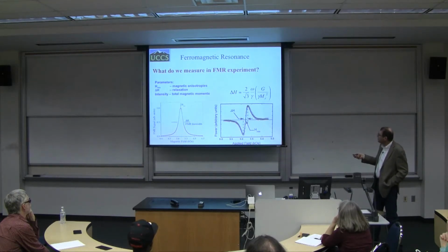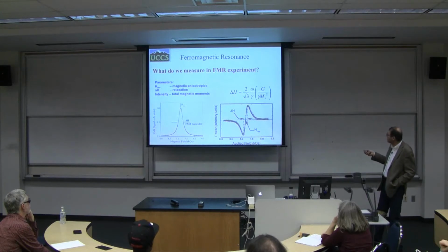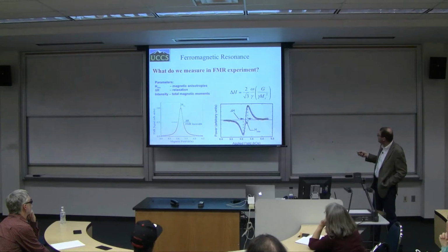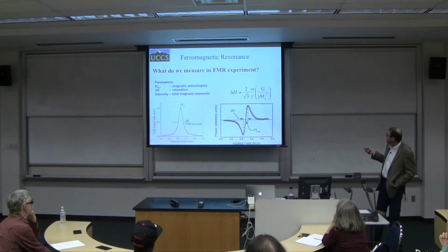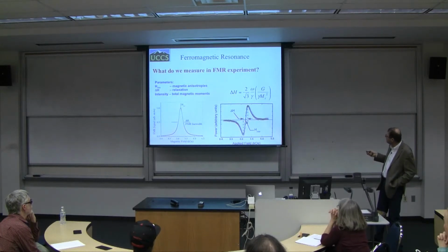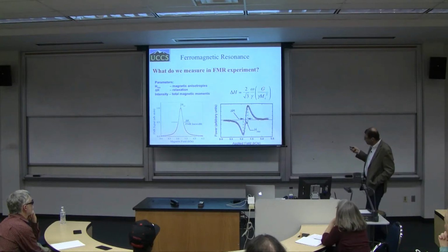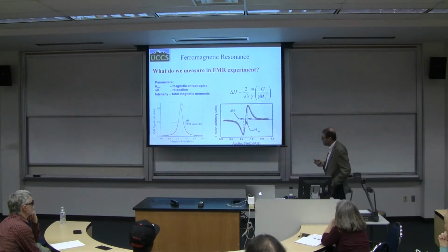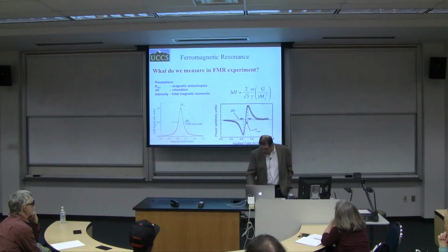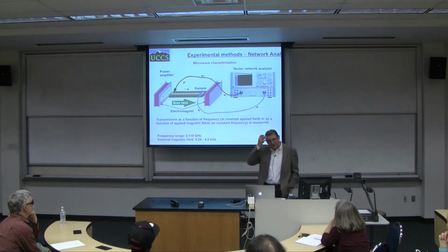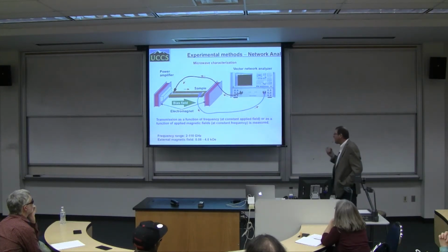What we very frequently do, we don't measure these measurements like this. We measure the derivative. Again, you have here examples of the dots representing the measured points, and the solid line is a fit. And you can connect the width of this double dip curve to the Gilbert parameter which determines the damping. Anyhow, I hope that I have convinced you that this is something quite powerful.